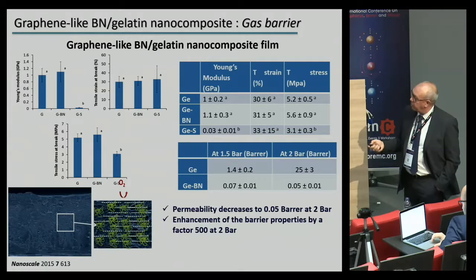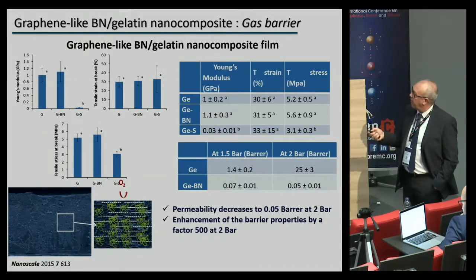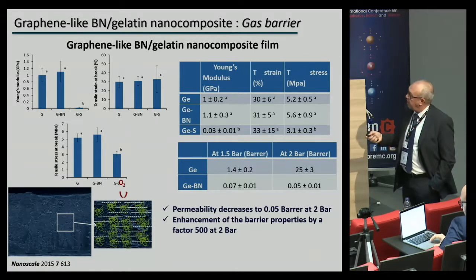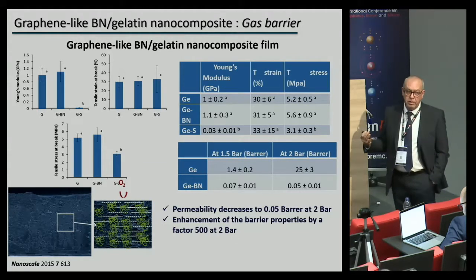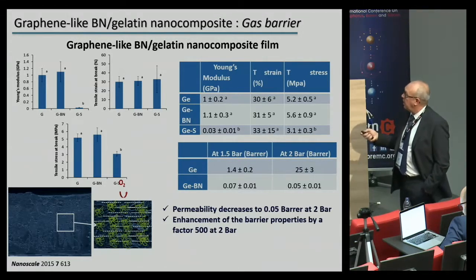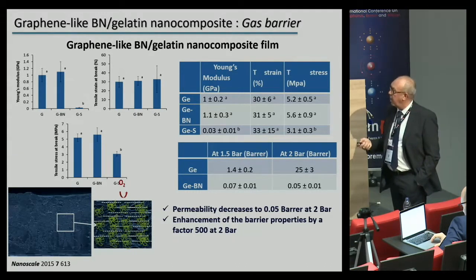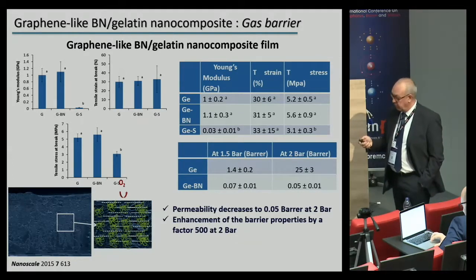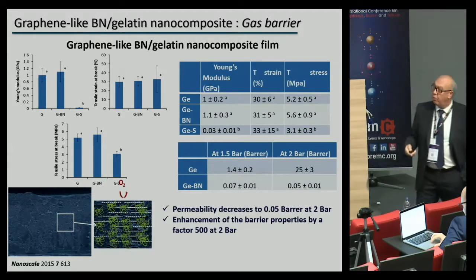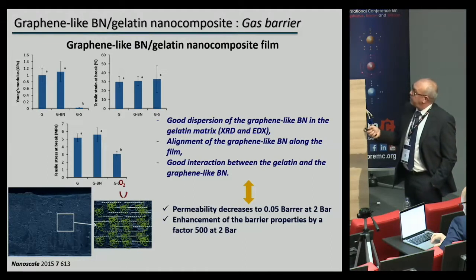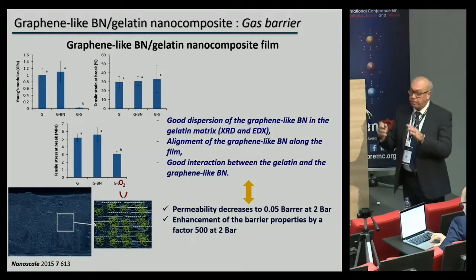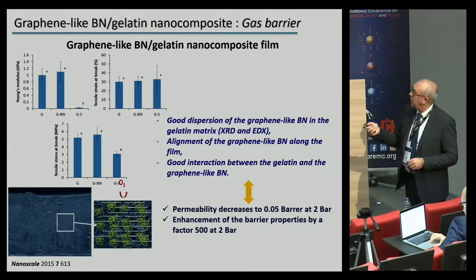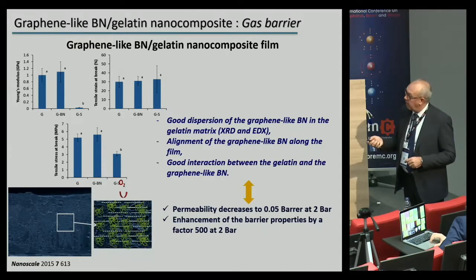Here you have the picture of the membrane, and this is the result of the permeability of oxygen through this membrane. I will not comment on the mechanical properties because I have no time to do that. You can see that the permeability decreased to 0.05 barrer. Barrer is a specific unit for this kind of permeability at 2 bar, and thus we have an enhancement of the barrier properties by a factor of 500 at 2 bars, which is very good, for example, for food packaging applications. This is related to the good dispersion of the graphene-like BN in the gelatin matrix, which has been shown by XRD and EDX, the alignment of the graphene-like BN along the film, as shown here, and also the good interaction between the gelatin and the graphene-like BN inside the membrane.